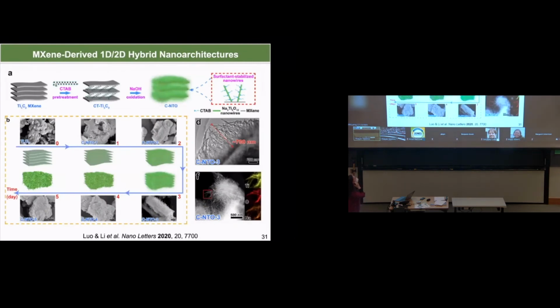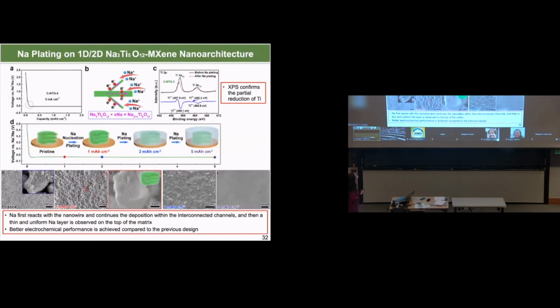Further, Dr. Luo also tried to improve this design by doing some nanostructure design within this interlayer. He tried to grow some very interesting nanowires within this MXene layered material. In this case, we achieve a better performance compared to the previous case, because once we grow all these nanowires, we get a 1D, 2D hybrid nanostructure. All these pearl-like structures can help to induce the sodium nucleation within the interlayer spacing, and eventually we also achieve a very smooth sodium deposition. I did not put the electrochemical performance here, but experimentally, we do achieve a better electrochemical performance compared to the previous MXene design.